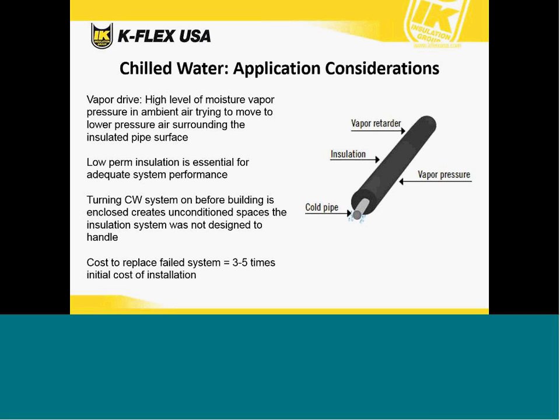Insulation is essential for adequate system performance. Some watch-outs here are also to turn on a chilled water system before a building is enclosed. This may create an unconditioned space that the insulation system was not designed for. The system is designed for indoor applications and the building is not fully enclosed. The temperature and humidity values may be at a point where condensation will occur even if the insulation is already installed. If a fibrous or any type of open cell insulation system is used in this case, you start getting moisture penetrating into the insulation system from day one, which could cause performance issues later on in life. And just a quick takeaway here as well, to replace a failed system is generally 3 to 5 times the initial cost of installation.